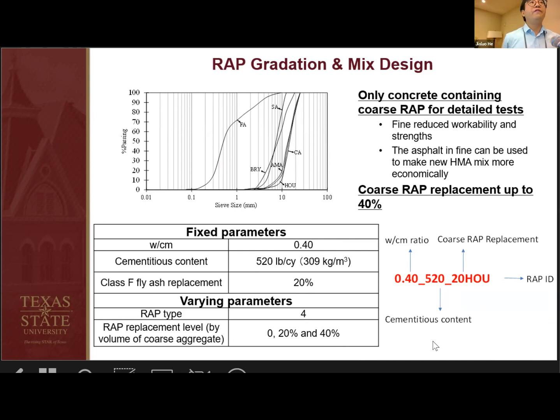We did some literature review. We found using fine RAP in concrete just did not work because it introduced a lot of strength reduction and caused a lot of workability issues. So that's why we only replaced coarse RAP, and only up to 40% by volume. Then we had 4 different mixtures, different types of RAP, and for each type of RAP we replaced 20% and 40% as coarse aggregate replacement.